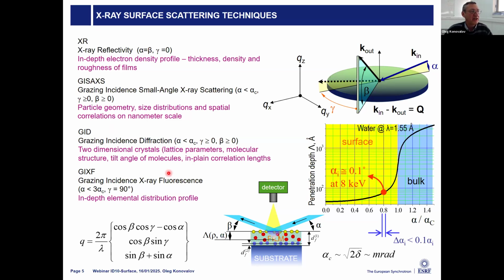And for traditional GID, these are big angles, so we can see diffraction from two-dimensional systems. In this case, we can see the lattice parameters. But if we have macromolecules or rod-like molecules, we can learn also about the structure of the molecule, the tilt angle of these molecules, or the preferential direction of the tilt. Additionally, if we measure the fluorescence signal coming from the surface, we can probe the near-interface elemental profile, and also see the electronic structure of the atoms of elements near the surface.